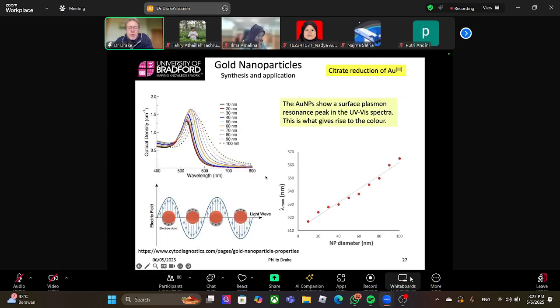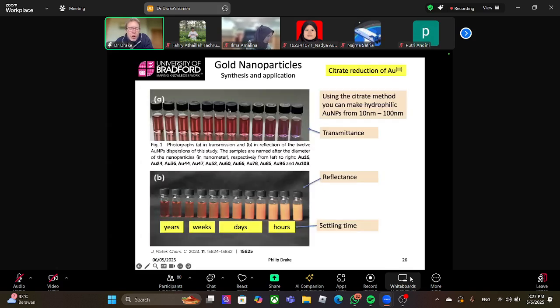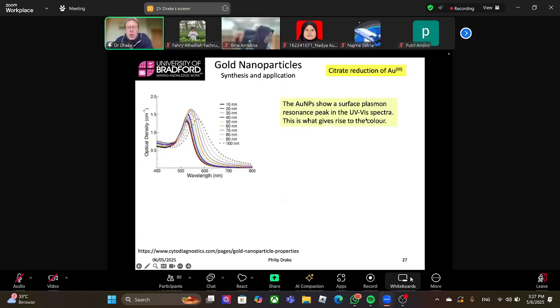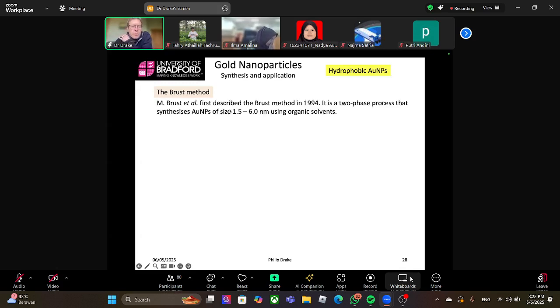So those were hydrophilic particles. These are all dissolved in water. We can also make particles hydrophobic, so we can make them dissolved in organic solvents. To do that, we use the Brust method. Brust first described it in 1994, it's a two-phase synthesis process. It can make very small gold particles, Au nanoparticles of about 1.5 nanometers to 6 nanometers, soluble in organic solvents.